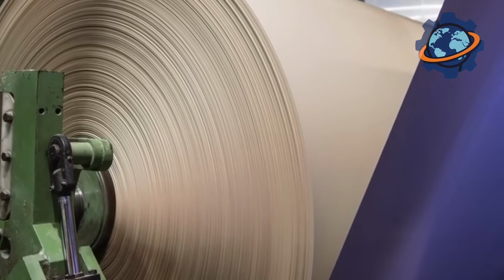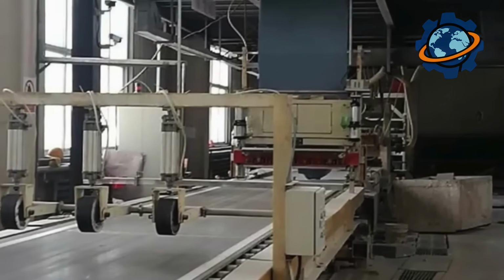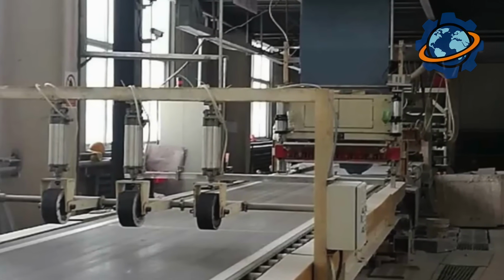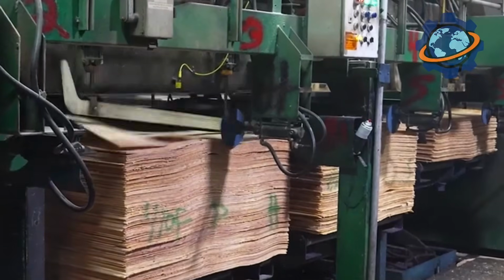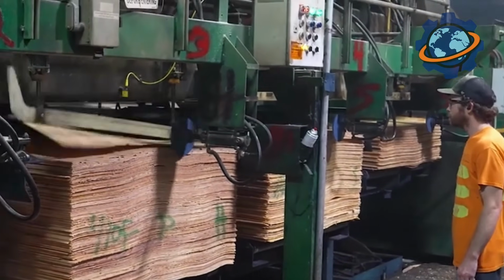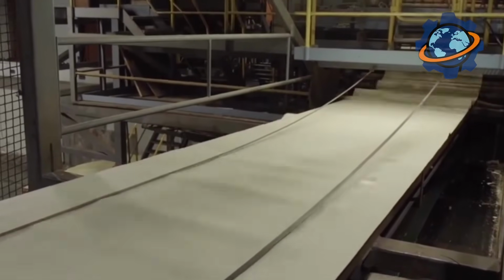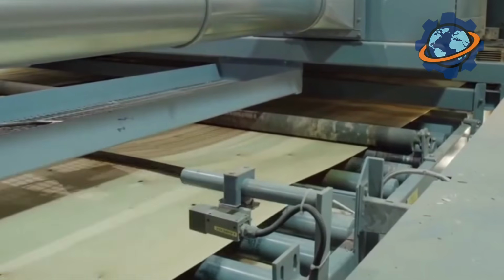This sandwich immediately passes between two rollers or under a forming plate, which compress it to a precisely specified thickness, for example, ½ an inch. The newly formed, still soft and wet sheet of drywall continues its journey on a very long conveyor, which is called the setting line. Its length can reach several hundred feet. As the sheet slowly moves, a real miracle happens inside it. The gypsum powder reacts with water. The rehydration reaction takes place. The gypsum turns back into a hard stone, releasing heat in the process. If you touch the sheet at this stage, it will be warm. In a few minutes, the loose mass becomes hard enough to hold its shape.